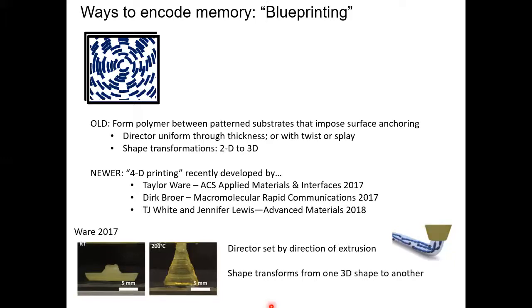There's another way, I don't think I have a slide for it, that's kind of interesting. You can use a magnetic field to orient the nematic liquid crystal. So if you, for instance, lay down thin layers of nematic liquid crystal and then apply a magnetic field that will orient just the free stuff that isn't cross-linked yet, and then shine the light to selectively cross-link part of the sample, and then maybe move your magnet, align the free liquid crystal another way, and then again, boop, boop, boop, you can just cross-link little voxels of the material, and you can do that layer by layer, as many cycles as you're willing to make on each layer.